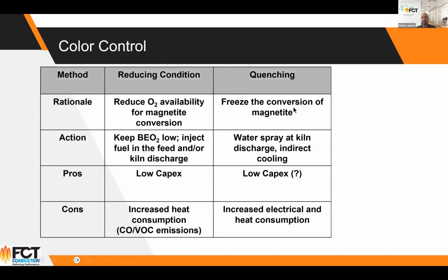So we try to freeze the conversion of magnetite. The hematite becomes magnetite. Magnetite is kept in its form as long as you freeze the material down to keep this phase still existing. You can water spray at the kiln discharge. You can have an indirect cooling.